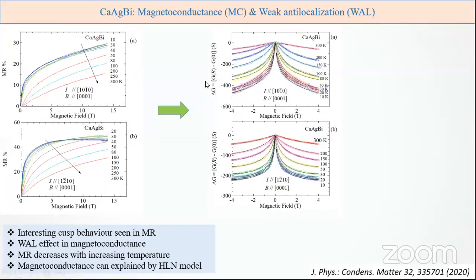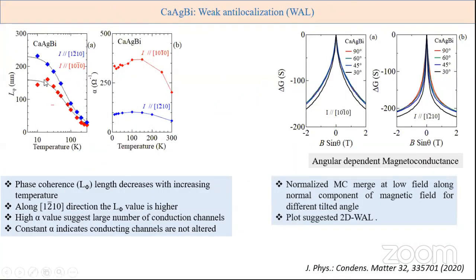For each temperature, we calculated the magnetoconductance from the magnetoresistance, and therefore we can calculate the alpha value as well as the phase coherence length for different temperatures. So here is the phase coherence length as a function of temperature. You can see that as the temperature increases, due to the phononic contribution, the phase coherence length is reduced. In both directions, it shows the reduction of this phase coherence length. And the alpha value is quite large for the two different directions.